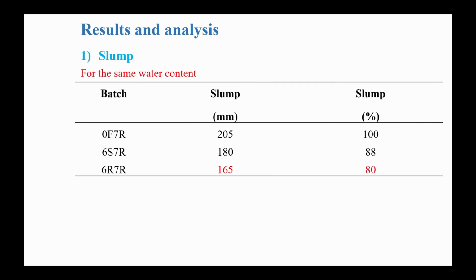According to the results which we got, this is for the same water content. The decrease in slump for the recycled steel fiber was high compared to the industrial steel fibers and compared to the plain concrete.